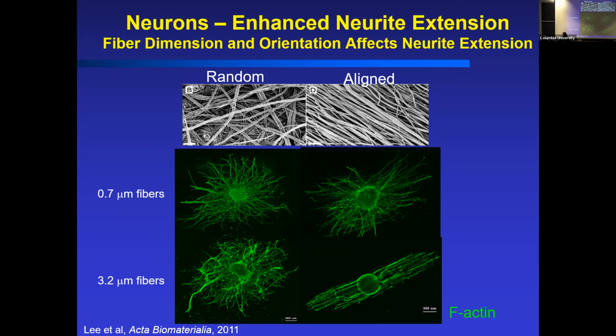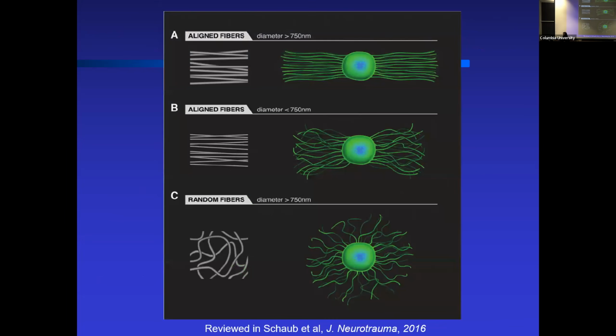So our take home from this is that you want, on a larger scale, micron-sized fibers, and you want alignment. And that helps to really get great extension of those axons. And others have also shown this, in a number of studies, that this really is key to be above a critical micron-sized dimension in order to achieve the greatest axon extension.